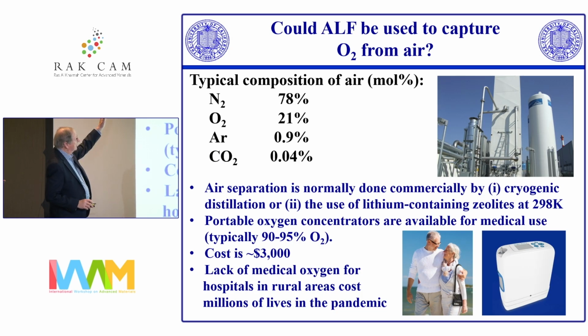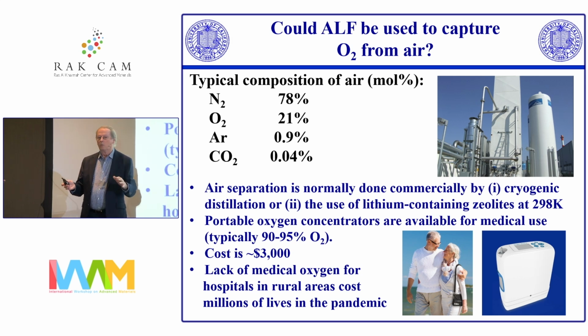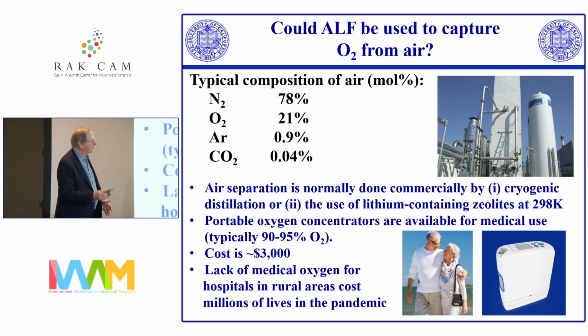If you get medical oxygen, it can be made one of two ways. It can be made with cryogenic distillation of liquefied air. That obviously takes a lot of engineering and expense. Or if you see these portable oxygen generators that people with breathing problems and so on carry around with them, those typically use lithium zeolites, something like lithium zeolite X. What happens with the lithium zeolites is that they preferentially absorb the nitrogen. And this works because the quadrupole moment of nitrogen is about 4 times higher than that of oxygen. So you get an interaction between the lithium and the nitrogen.